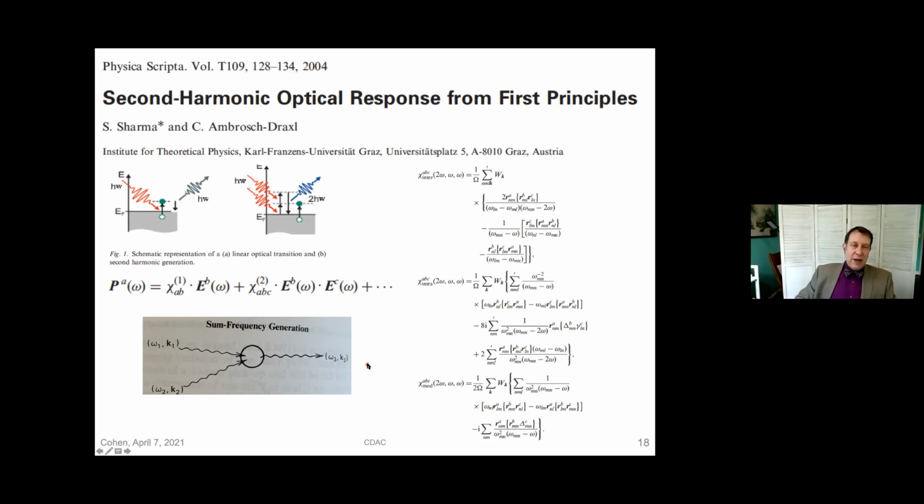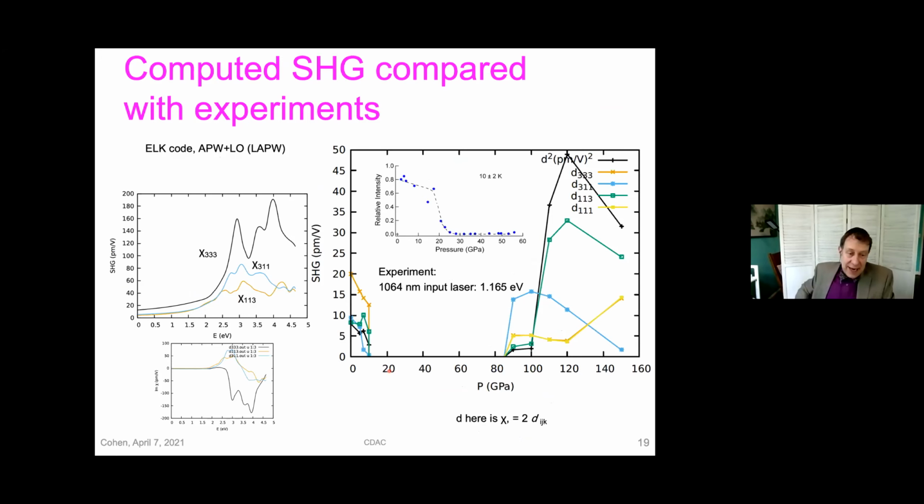And we're using here a theory which is based on perturbation theory for non-degenerate states, and so we have to do some tricks to get rid of all of the degeneracies. So we have to shift the K-point grid so that we only deal with non-symmetric K-points, and we have to do a lot of things to make sure that we're getting robust and good results. So we've done these calculations, and they really look quite similar to the experiments.